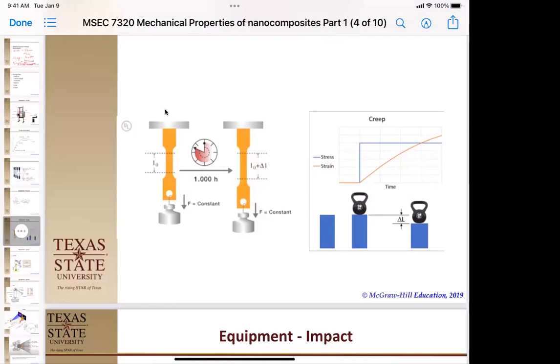But let's say you want to put a nanocomposite under a generator. You don't want that creep number. You want this creep number. In fact, you don't care about tensile strength anymore. You want to know if it's going to deform over time at the operating temperature. So you put a relatively realistic load on your sample per unit area and measure that over unit time.